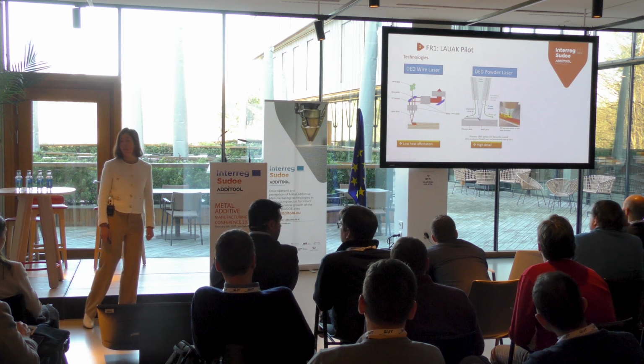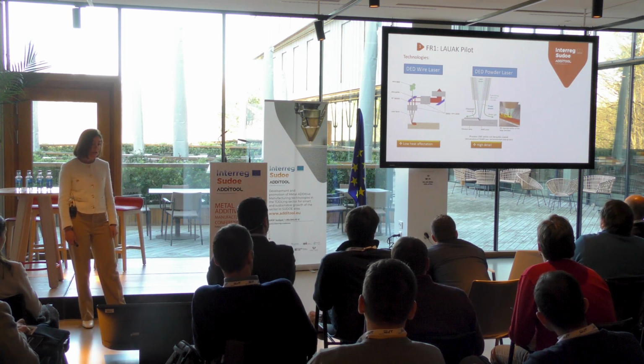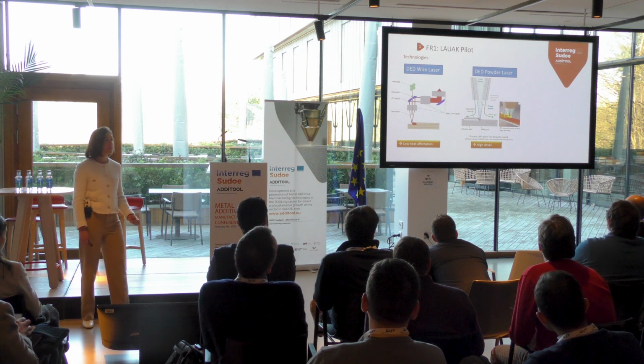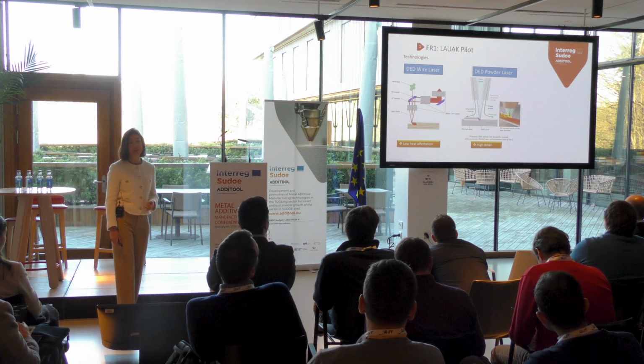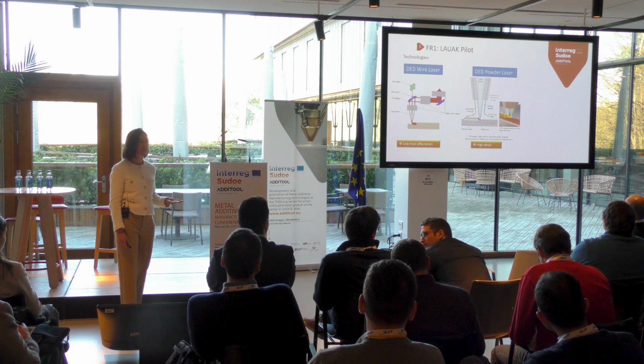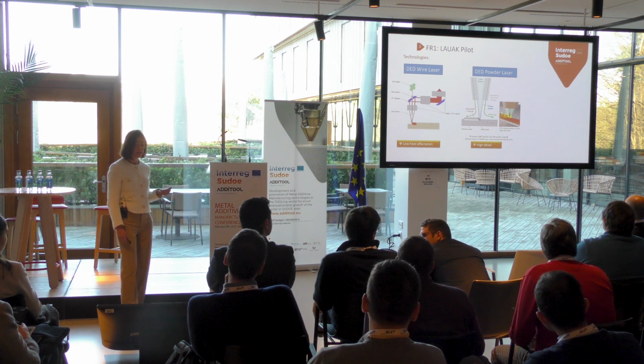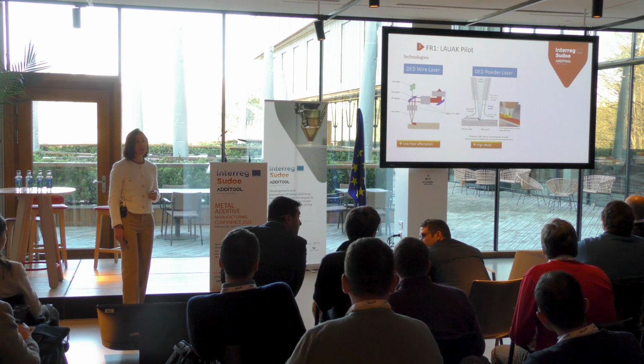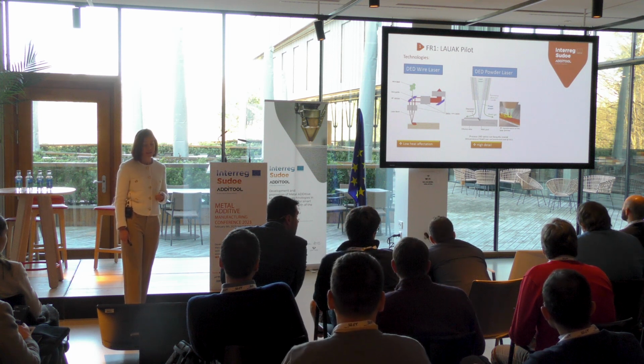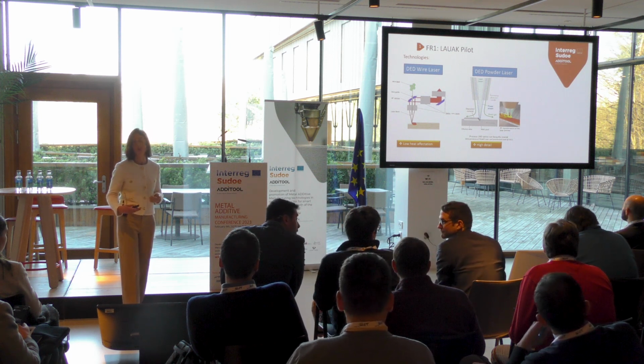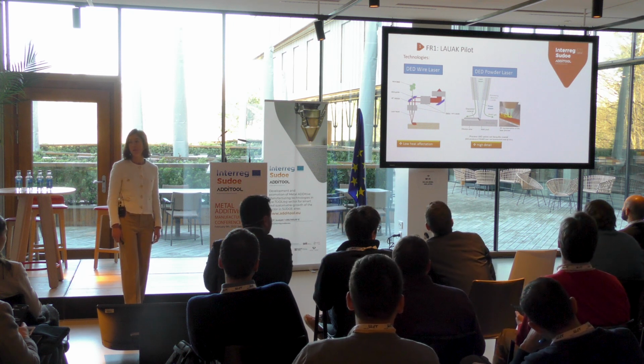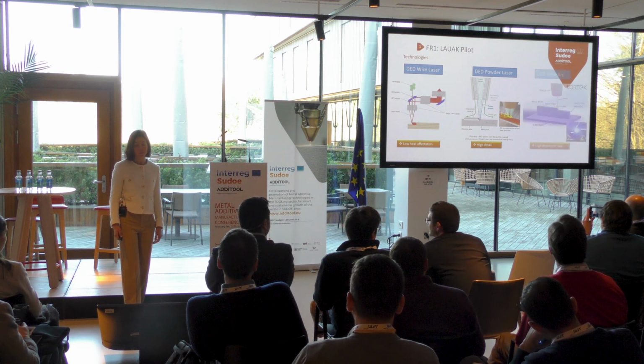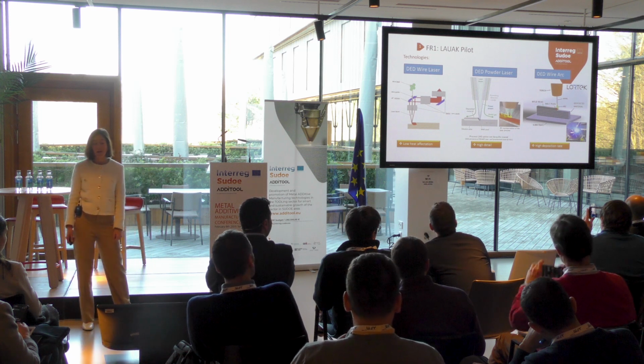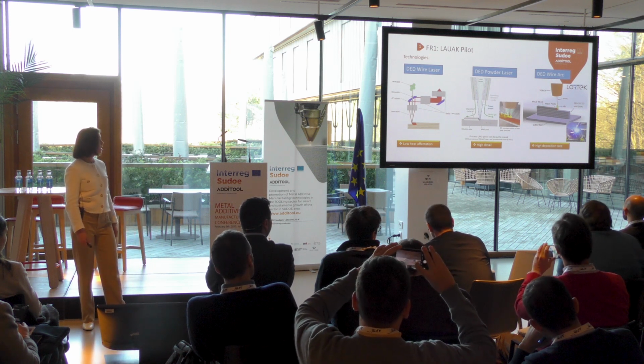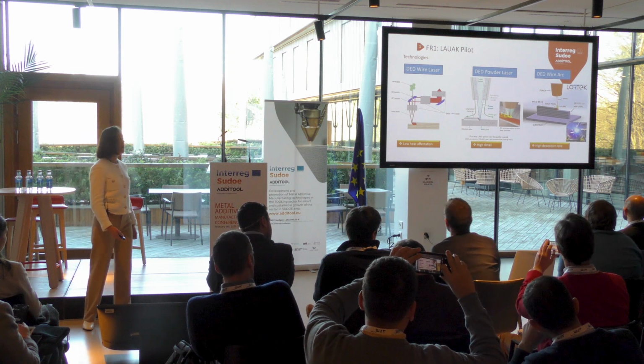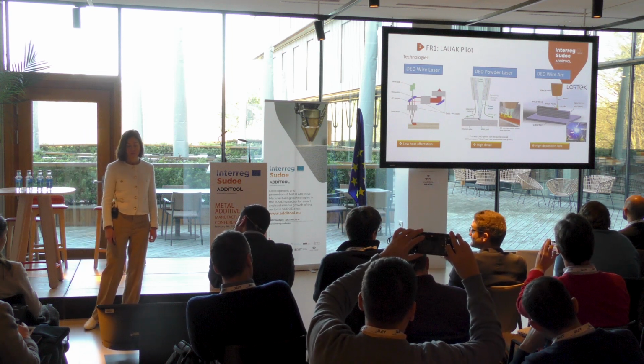In the case of powder laser, the use of powder gives us the possibility of obtaining high detail, so the final machining step will not be as long as for other surfaces. Finally, wire arc is the one that can offer a very high deposition rate.